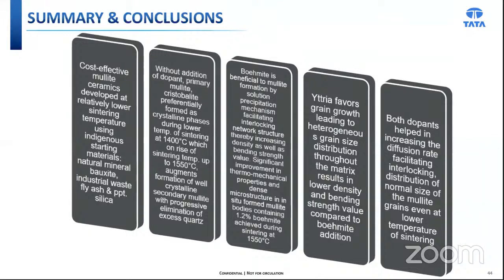Boehmite is basically beneficial for formation of the interlocked microstructure with homogeneous morphology, because for this the RUL value as well as the strength and the other desirable properties is very good. Yttria favors grain growth, but because of the higher percentage of the yttria, throughout the matrix the abnormal grain growth is observed, which may also help increase the bending strength. But compared to yttria, the boehmite addition is better, and both dopants addition help in increasing the diffusion rate, facilitating interlocking and distribution. So we have observed that the optimum percentage is better compared to the individual yttria or boehmite additions.